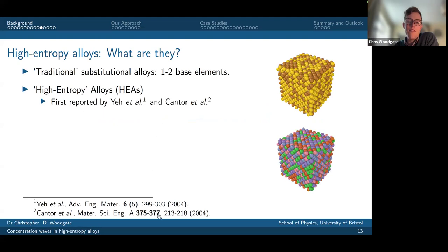So there were these two seminal papers published in 2004, pretty much concurrently by 2 different experimental groups, where they showed that for certain combinations of elements, it's possible to stabilize single phase solid solutions containing, some people say 4 or more, some people say 5 or more, but I generally just say 4 or more elements in near equal ratios, so where the concentrations of each element are near equal.